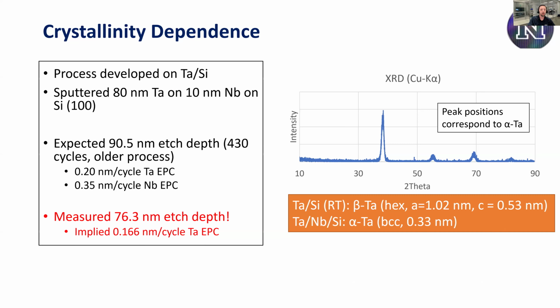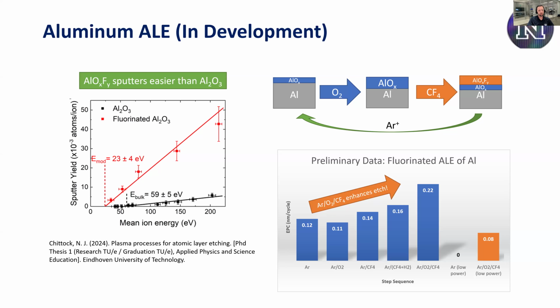Another thing that we're doing right now, we're just starting on ALE of aluminum. Our approach here is a little bit different. We tried to form TMA, trimethyl aluminum, as an etch product for quite a while. It didn't work out; we didn't really get any etch from that. But we'd had this idea in the back of our minds for a long time: we don't want to just physically sputter aluminum, but if we could make aluminum oxide, that might be really interesting because that's a pretty hard material to sputter.